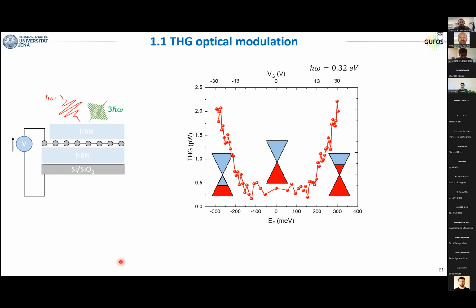Before I start with that, I point out that this time we are using a different type of device. We don't have only graphene on silicon dioxide, but this time our graphene is encapsulated in hexagonal boron nitride, so much higher quality. We changed the photon energy to 0.3 electron volt. Now I go back to the question of George.